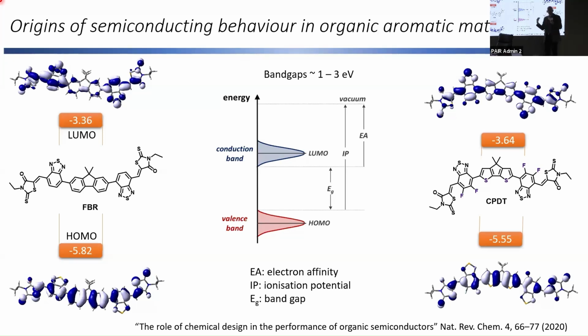And what we see is that when we bring it down below the half potentials, you can add a little bit for a kinetic effect of overpotential. But when you bring them down, then they become operationally very stable. So I've been able to avoid these thermodynamic redox processes as an issue. With P-types, the original thiophenes were quite unstable because the HOMO energy level was quite high in energy. So it could be oxidized by oxygen. So you could take the electron away in the same way.